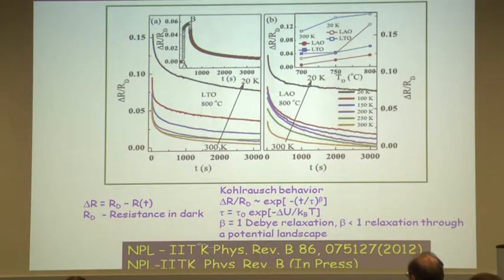So if I look at this behavior, I can work out the recovery process. I define this quantity delta R over R dark, where delta R is the resistance in dark minus the resistance at time t after exposing it. And you will see that it follows this stretched exponential behavior with an exponent beta.